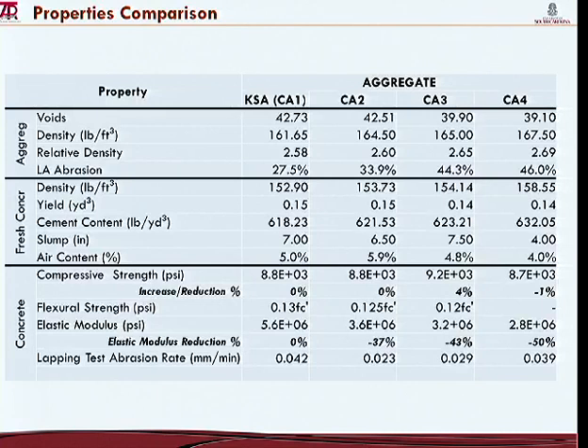So measured as between 33 and 46% as opposed to 27% loss that we had in the limestone. And I will discuss this in a second once I get down to the lapping test abrasion.